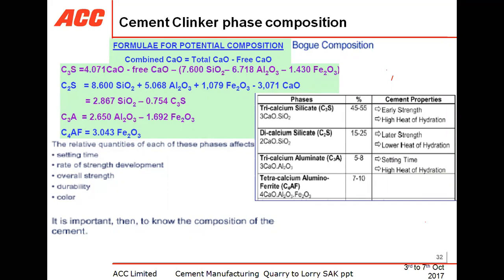Because these four phases are very important in clinker. Because it directly affects your setting time, rate of strength development, overall strength, durability, and color. So in the table you can see these phases, and on the right side cement properties are shown. Tricalcium silicate C3S, which is present up to 45 to 55%, is responsible for your early strength and high heat of hydration. Second one is dicalcium silicate C2S, which is present up to 15 to 25% in clinker and is responsible for your later strength and low heat of hydration.